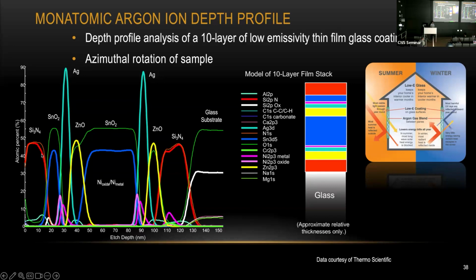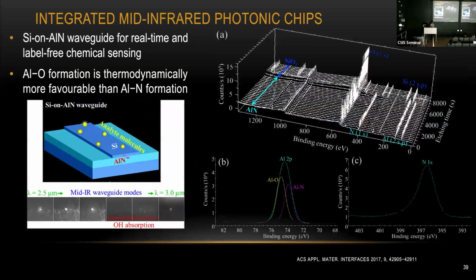So for instance, for the data here, you can see the top layer is actually some silicon nitride, and it's only about 15 nanometer. Now we start to see some tin oxide, and below the tin oxide, we see some silver. So you can go through the entire stack and eventually you just see your glass signal, which means we have etched through the entire stack of the thin film. That will be very useful if you see something unexpected.